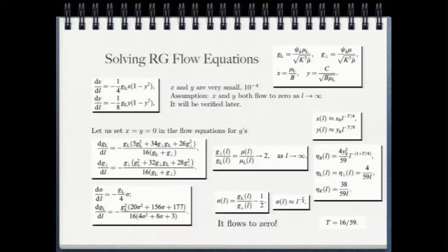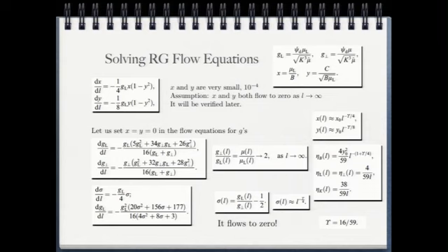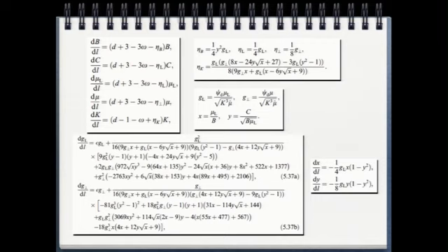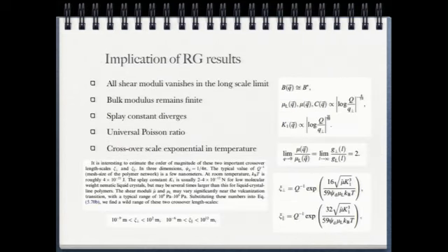Basically, it took me 2 years to work out the flow equations and understand the consequences. So these are the details. And we found the eta exponents, which are the anomalous exponents for these elastic constants. And we found that there's a universal ratio between G_perp and G_L. G_L divided by G_perp is basically half, the fixed point value.